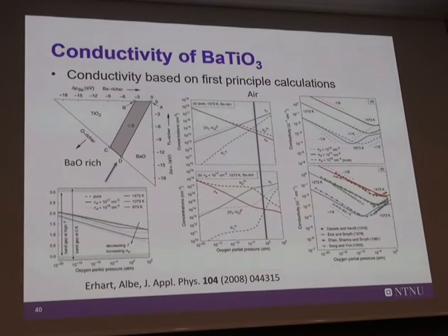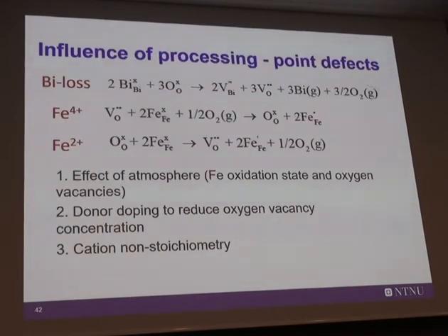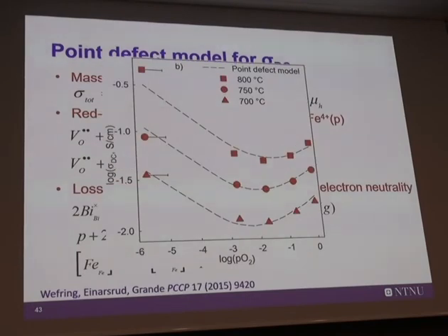So that was also the point with the bismuth ferrite, that you could show that the P-type conductivity in bismuth ferrite is probably not very strong. It is not low. You don't need to go low in PO2 before you have a dominating N-type conductivity. And that was maybe the most important part of this work, that you can show that we have iron 2+ or N-type conductivity quite playing a role in bismuth ferrite. And it's not a very high PO2 where this minimum is normally located.